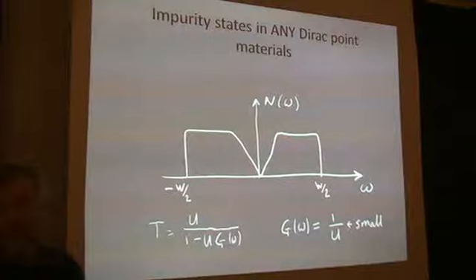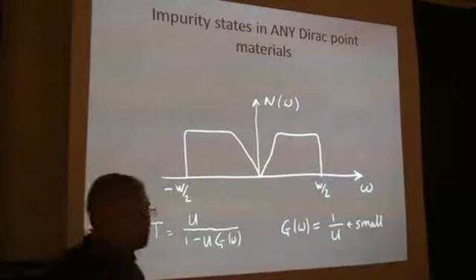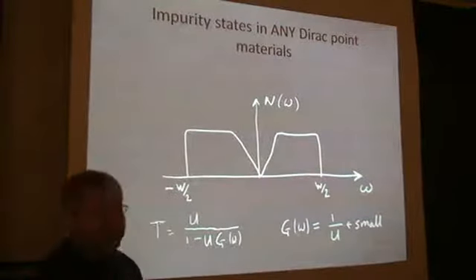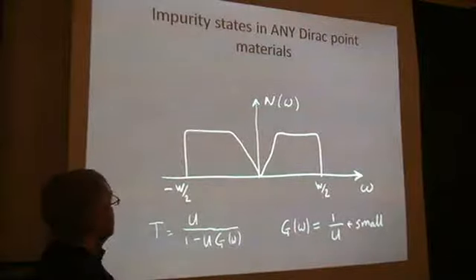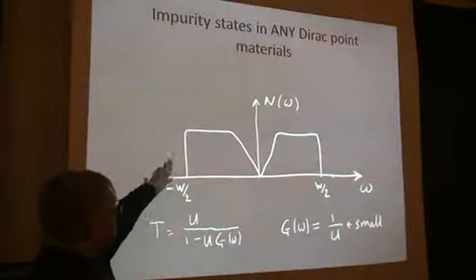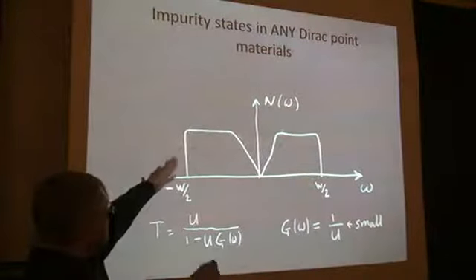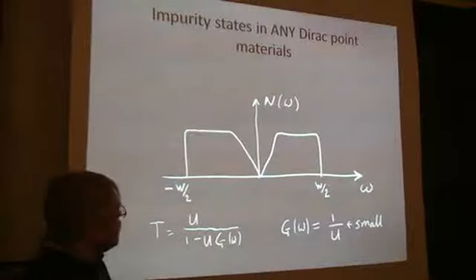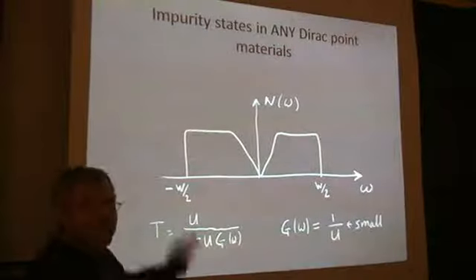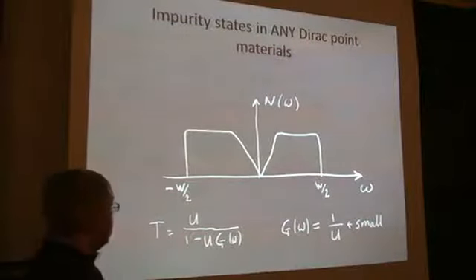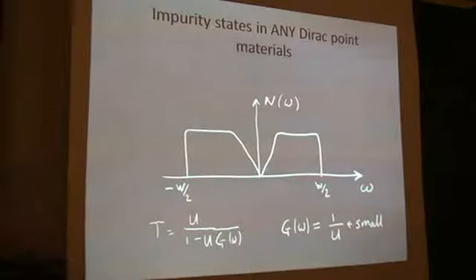All right. So I'm going to point out something very simple. And so we're going to solve the kind of impurity problem in the graphene and d-wave superconductor graphically. So if I have a simple metal, and by whatever fiat I created this supposed density of states, which looks like a V-shaped density of states, of the bandwidth W. I want to look at the effect of the impurity scattering, and I want to go beyond the Born scattering.